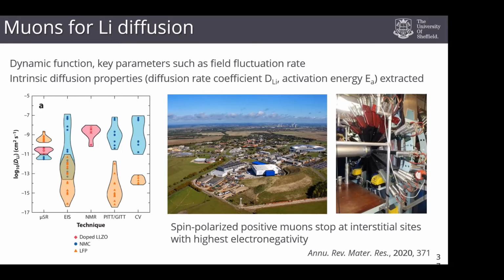We use muons to interrogate lithium diffusion. So we go down to the ISIS neutron and muon facility, that's these buildings here, right next to the Diamond synchrotron for X-rays. And we use their muons. What's a muon? A muon is a positively charged particle that has a spin associated with it. They occur naturally in the atmosphere.